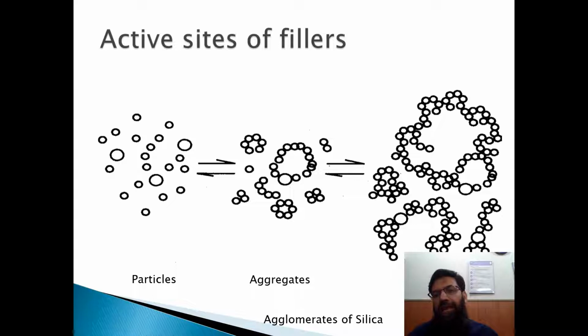The dispersion can also be enhanced by using different dispersing agents, just like we can use different glycols, which help us to disperse the silica in the different polymers. But dispersion alone is not the main requirement, because sometimes we disperse the silica in the polymer and get better dispersion, still we